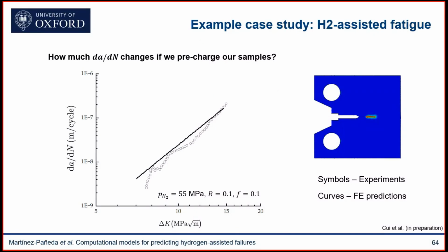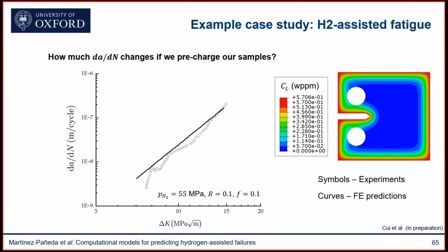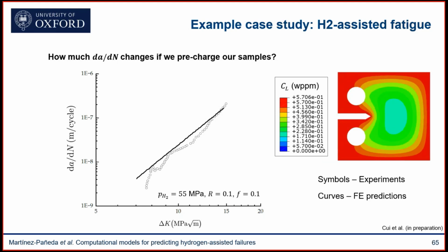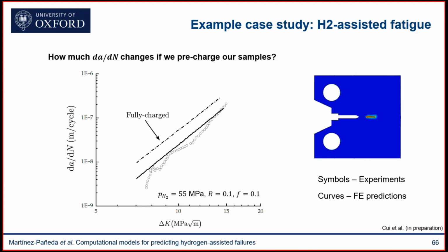So we wonder, okay, maybe this is not the most relevant scenario. It could be if you have an oxide layer, but maybe it's not the most relevant scenario to real applications where you may have your pipeline or pressure vessel exposed for a very long time to hydrogen. So what we do in our experiments is we pre-charge our samples. And unlike the experiments, in our virtual experiment, we can do this quite fast. That's the reason why they don't do it in practice. So we can pre-charge our samples quickly, and then we run the fatigue experiment. And this is what we see.